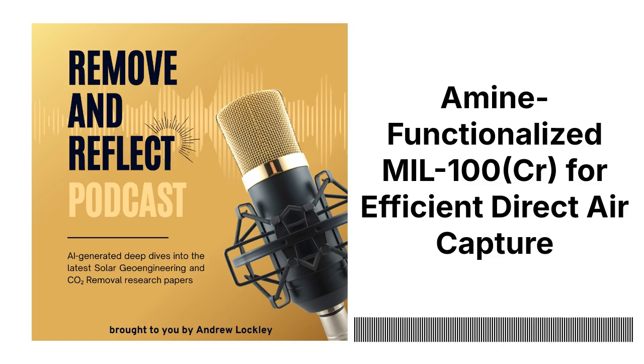Exactly. Okay. And the best one was the MIL-100 CR modified with PEI. The PEI, okay. Yeah, it had a CO2 adsorption capacity of 1.21 millimoles per gram. Okay. That's 2.5 times better than the unmodified MIL-100 CR. Yeah. Which was only 0.48. That's a big difference. It is. Okay, so PEI is the winner so far. Yeah, it is.